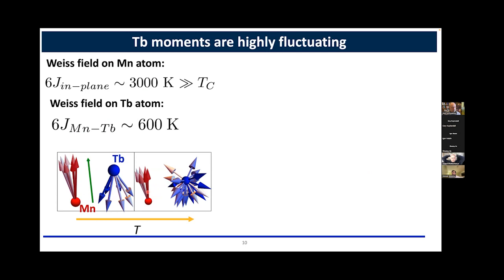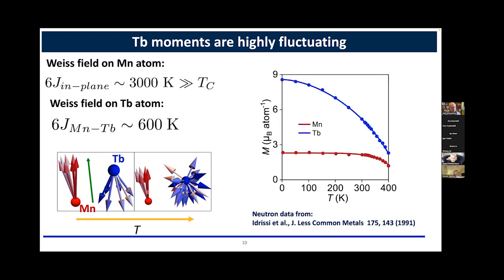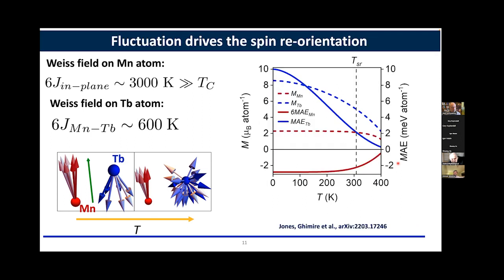And it is consistent with the experimental observation also. Interestingly, there was a neutron experiment done way back in 1991, and they reported the magnetic moment on both manganese and terbium atoms. And we just replotted it here. If we look at the moment of the manganese atoms, it remains pretty much constant over a wide range of temperature, and it decreases slightly at high temperature. Whereas the moment on terbium sharply decreases. And that is one thing to think about: the terbium moments are losing moment by the fluctuations, right? That's the case.